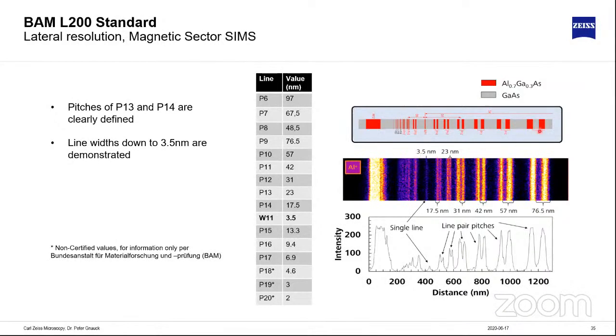So, for example, we're looking here for the aluminum signal, and what you can see, we can nicely resolve lines of 70 nanometers, 57 nanometers, 40 nanometers, 30 nanometers, 17.5 nanometers. With EDS, you would have no chance to separate these lines, and we can detect a single line in the range of 3.5 nanometers. So this is the resolution that we can achieve in the analytical mode in this tool.